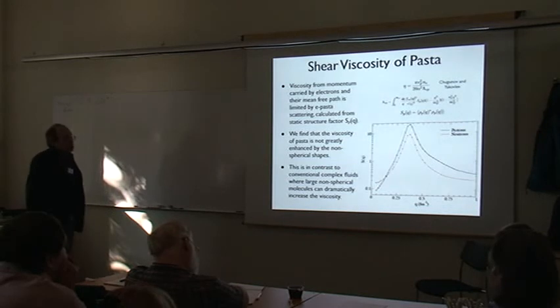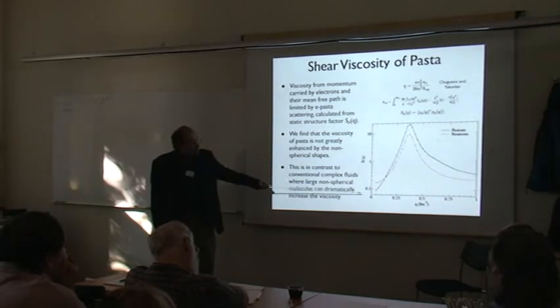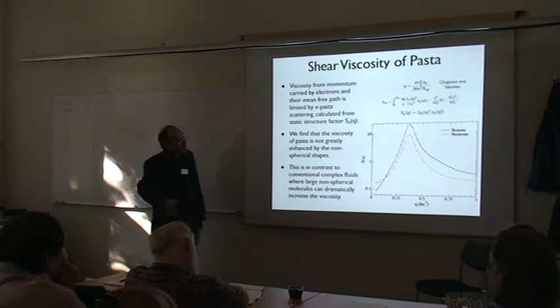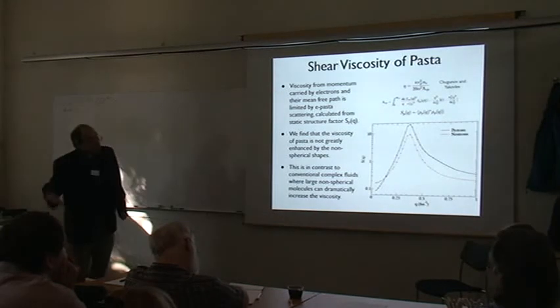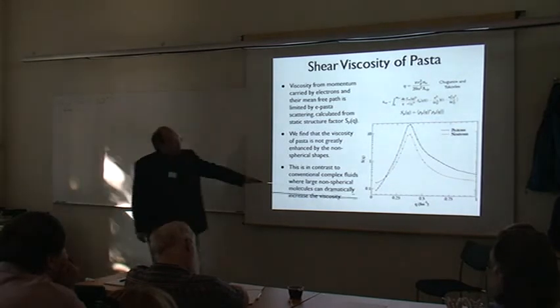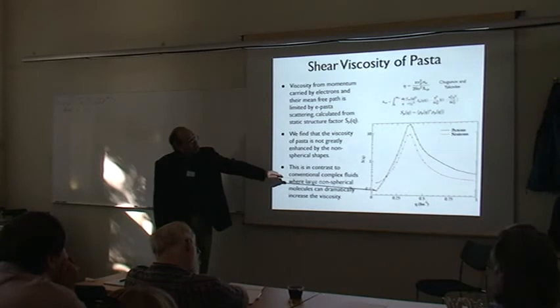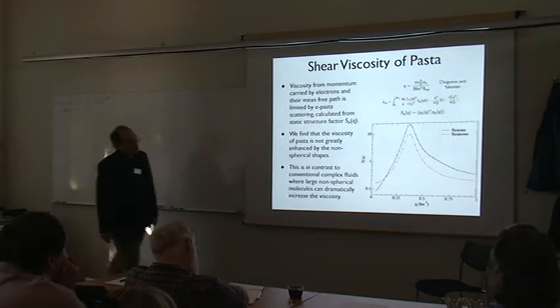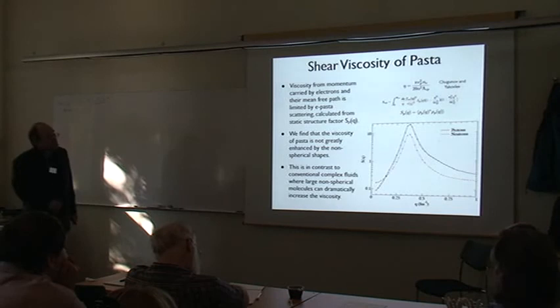For example, at low Q, you can have neutron density fluctuations, but any proton density fluctuations at long wavelength get screened. So S of Q goes to 0 faster for the protons than for the neutrons. At low Q, you see that difference.